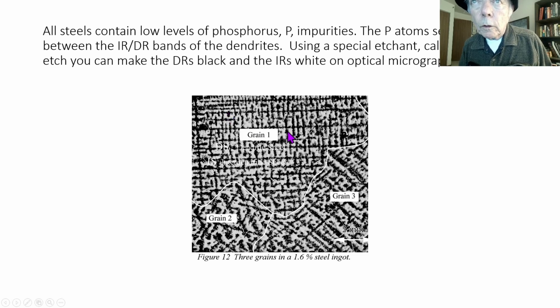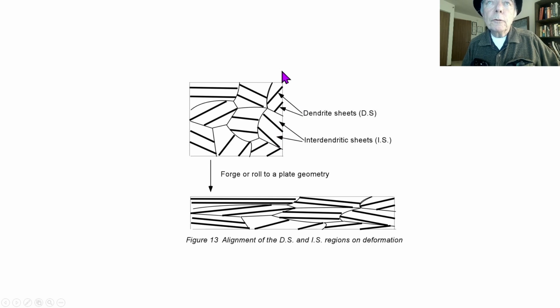also. Notice that when you switch across the green boundary, you get a sharp rotation in the orientation of the alignment, and that's due to the crystal structure of the grains being different in the two grains. Now here's what happens when you forge one of those little ingots down. These little regions I've shown schematically as regions of dendrite sheets and interdendrite sheets. Well, on forging, there's an alignment that occurs due to the fact that you're squashing this thing down to a very, very much smaller size.